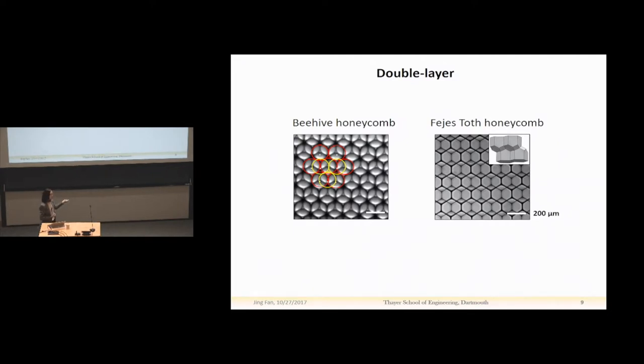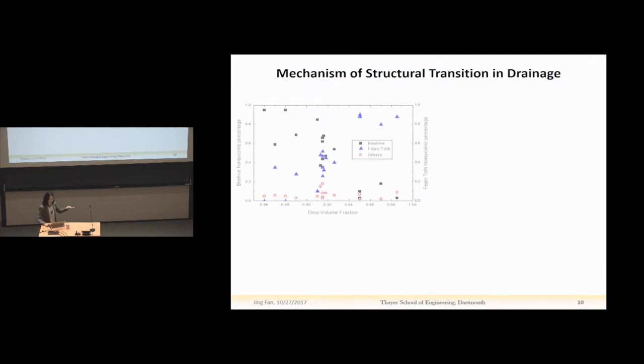So the system is driven by surface energy to take a structure with the minimum surface energy, which is proportional to the surface area, right? So then to test our hypothesis, we examine 16 independent regions of interest, which you can regard as 16 independent samples. Each sample has about 1,000 drops and over a wide range of volume fraction. Then we count the number fraction of each structure, beehive honeycomb and FT honeycomb, in these 16 samples.